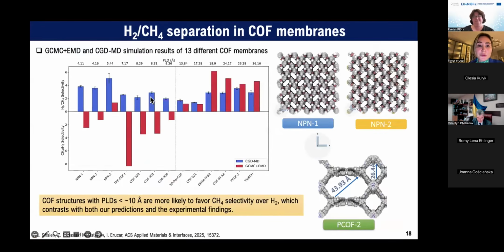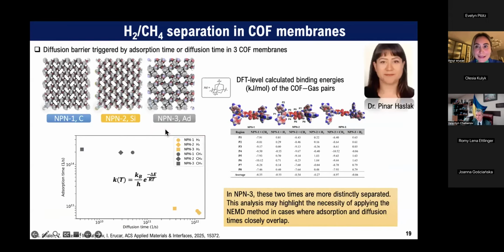Then, in order to understand better, we modeled 13 different COF membrane structures, and we recognized that something is interesting here. If you look at this curve, we see that there may be a threshold pore limiting diameter: if the pore limiting diameter is less than 10 angstrom, these structures are more likely to favor methane selectivity over hydrogen. You can also see this NPN family that I mentioned at the beginning of my presentation. Here, NPN3 is very interesting because we have the same results, although these materials have pore limiting diameters lower than 10 angstrom. So here we want to understand the diffusion barrier triggered by adsorption time or diffusion time.